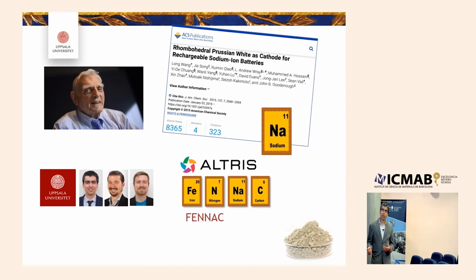And we were lucky that it happened, that we found a method to synthesize this material at room temperature or slightly elevated temperature with no need for extra high pressure. That was when we launched this spin-off company called Altris in 2017.